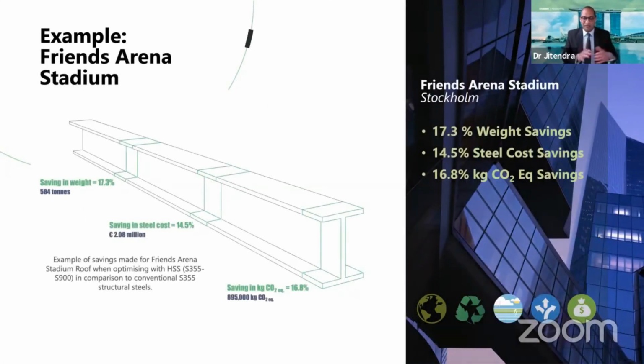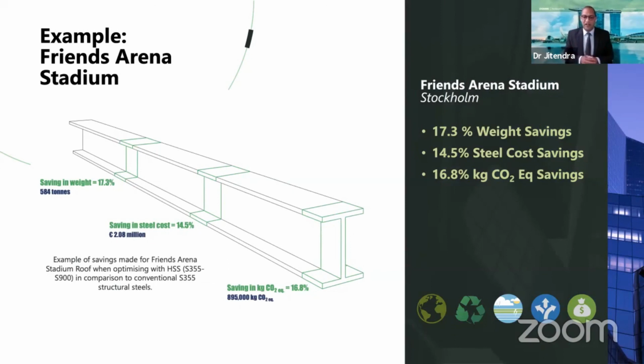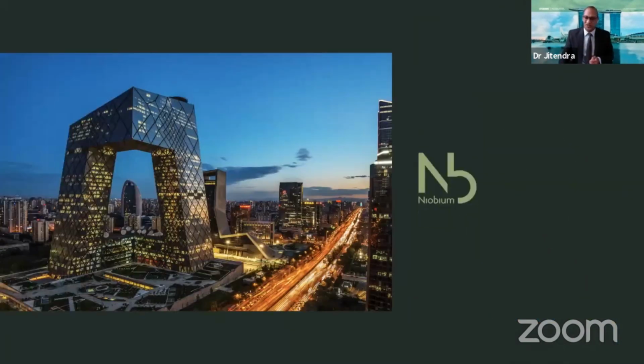And just to summarize that, for that structure, which ended up using higher strength steels, they were able to have savings of about 17% in weight, almost 15% in costs, and about 17% in kilograms per ton of CO2 savings. And you can see there that in tonnage, it's about 580 tons of steel that was saved, and the cost of that was about 2 million euros. So you can imagine for something like a sports stadium, that's a significant cost savings to be made. And the environmental footprint, you can see there were savings of around 900,000 kilograms of CO2 equivalent. So real savings to be had here within our users of steel.